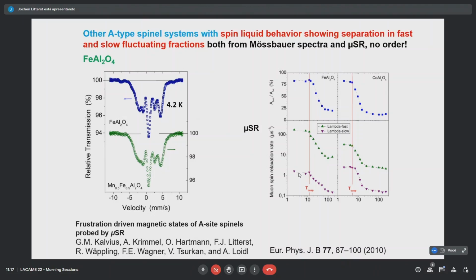Now, the other A-type spinel system I wanted to show you, that is an aluminate. Also here we will see it's a spin liquid system which doesn't show real magnetic order at low temperature, but we have a separation in fast and slower relaxing parts. Here you see the Mössbauer pattern, you see the non-magnetic part, and you see a slowly relaxing magnetic part. If we go to the muons at high temperature, once again you see two contributions, one fast fluctuating and one slow fluctuating, and a saturation in fluctuation frequency if you go to low temperature. So it's not a completely freely fluctuating system, it's slowly fluctuating, but it persists.